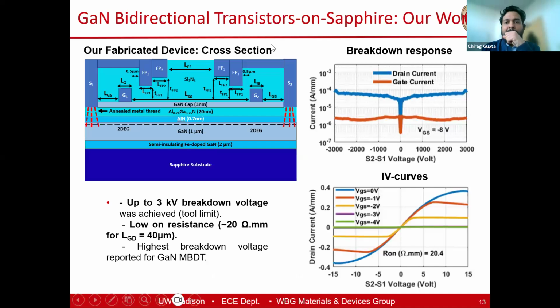So we went ahead and fabricated devices on sapphire. This was homegrown material where we had iron doped gallium nitride on sapphire. We deposited AlGaN GaN, nothing too fancy, very similar 2000 mobility material, close to 300 to 400 ohm per square sheet resistance channel. So very standard D mode transistor.